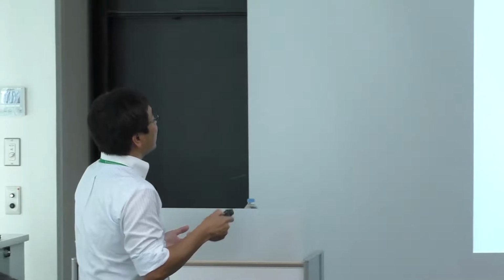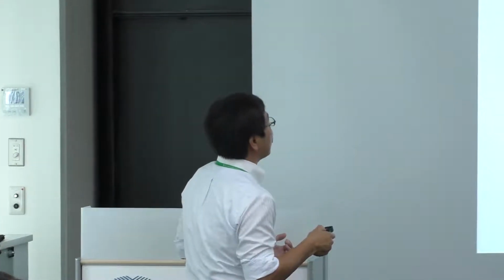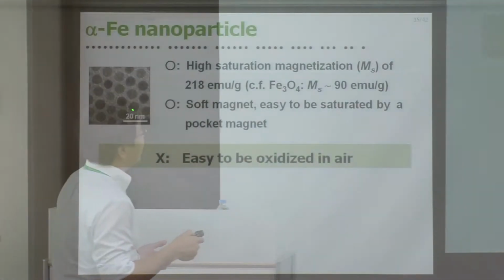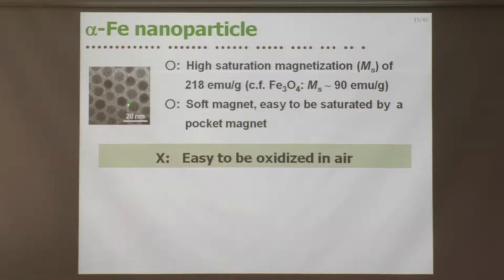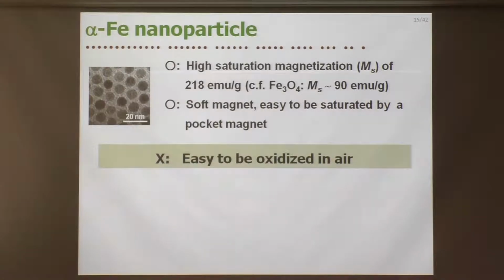Here shows a TEM image of the alpha iron nanoparticles I synthesized. They have a diameter of around 10 nanometers or so. If we expose these nanoparticles to air, what happens? You may imagine they will burn immediately. So it's a big problem, because we want to find an application for alpha iron nanoparticles in air. We should solve this problem.